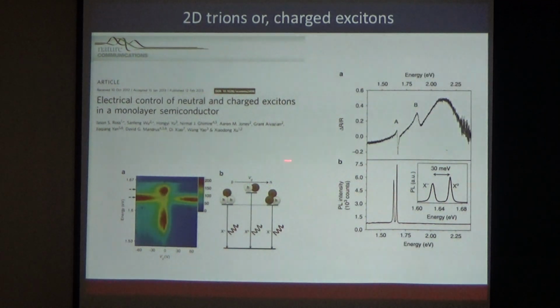And this is an experimental paper where they first observe the A and B excitons in this material. The origin of this B exciton is that this material also has spin orbit coupling, as the valence band is also split, and so they are defined by that spin orbit splitting energy. So this is an A exciton, and we are only focusing on A excitons. This is an absorption curve, but in photoluminescence, which is not visible in the absorption curve, you see two peaks here. One is separated from the other by 30 milli-electron volt below this A exciton. So this is basically the bound state of the exciton. This is called the trion peak.